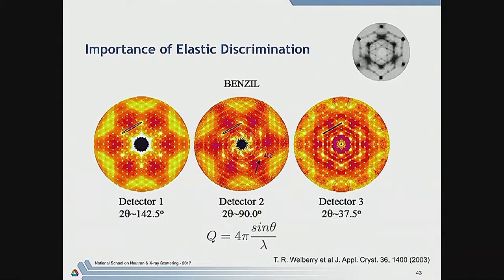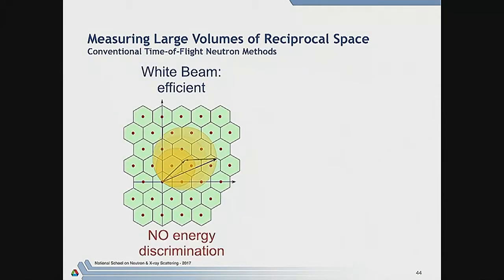And so they inferred from that that probably some of the scattering was inelastic. And that's almost certainly correct. How do we tell? Well, it turns out now here at the SNS we can. And that's because there is a machine called CORELLI, which aims to combine the efficiency of a white beam instrument. So this is sort of how a machine like TOPAZ covers reciprocal space: it has a whole range of wavelengths, and so it's measuring on a whole set of expanding Ewald spheres as a function of wavelength, and it fills the volume of reciprocal space that way very efficiently, okay?